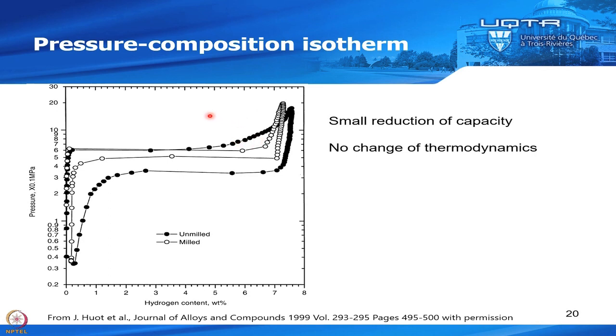But how do you define equilibrium? You define equilibrium when the pressure doesn't change. Okay, so you expose your material to that pressure, and then you see that the material doesn't absorb hydrogen anymore. So you say, well, this is at equilibrium. But if the kinetics is very, very slow, then your apparatus thinks that you reached equilibrium, when actually it's not at equilibrium. So this is due to the very slow kinetics.